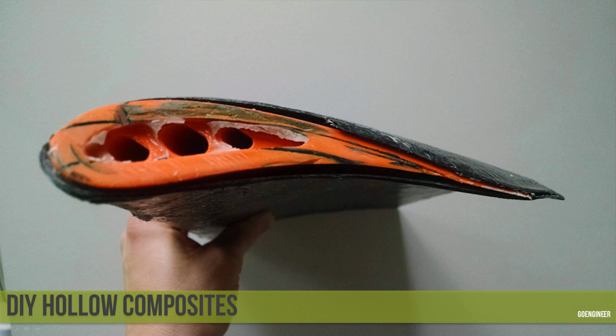Here's the top of the part. You can see where I didn't quite lose the spar, but I did get some delaminating between the two. So the same thing happened on the top with the small spar as it did on the bottom. And again, that goes back to promoting the bond between the composite and the ABS, and also maybe thickening up the composite as well. I only did 3 layers, and at 3 layers, the composite's still quite flexible. So I think if I did something a little bit thicker, it might also be less prone to pull away.